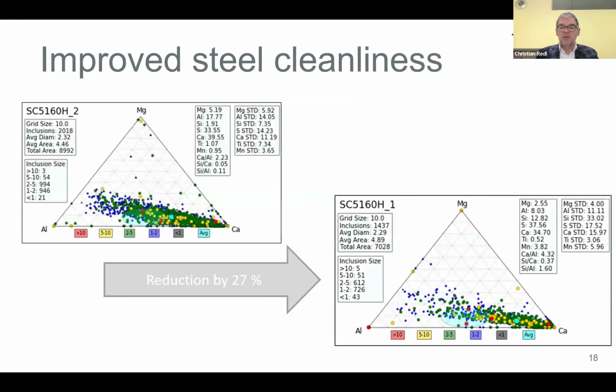Once again, an example from Nucor Steel. Also, steel cleanliness is improved. Here we see a reduction of the inclusions by roughly 27%. So this is due to this very good slag metal interaction, where a lot of inclusions can be separated in the slag. Of course, there is also a modification of the inclusions. This is a topic which is also discussed very broadly in the literature. What is the mechanism behind this inclusion modification and inclusion removal during vacuum treatment?